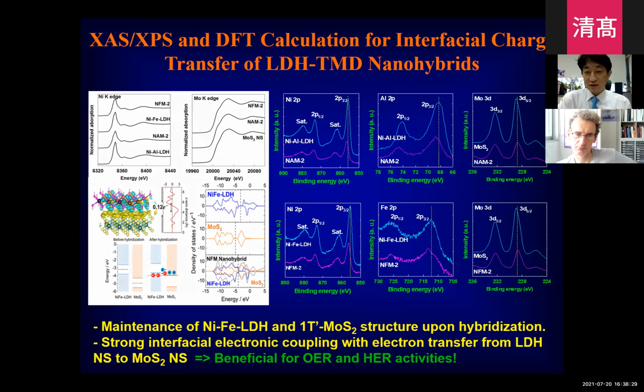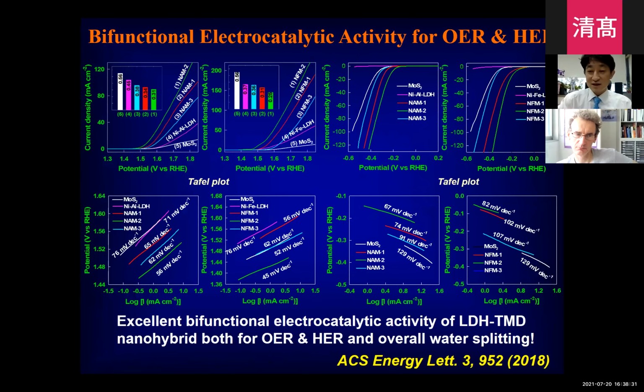The basic idea of this study is to synthesize a bifunctional electrocatalyst material, because the LDH is a well-known OER catalyst and molybdenum sulfide is a well-known HER catalyst. So as you can see here, such a layer-by-layer ordered hybridization is very effective in enhancing the OER activity of LDH and the HER activity of the molybdenum sulfide. The resulting material can be effectively applied as a catalyst for overall water splitting.